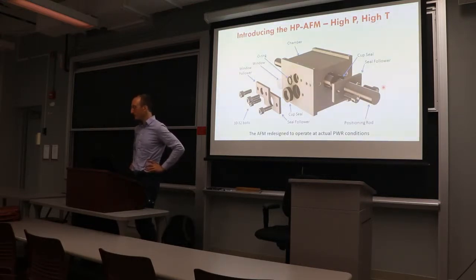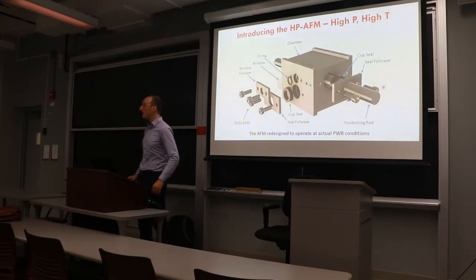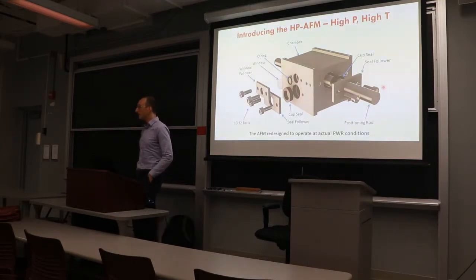What about thermal conductivity of these coatings? Doesn't matter. They're so thin. They're not as good as metals, right? These are ceramics. They're often not too good. But we only apply 1 to 200 nanometers. Like I mentioned before, the coating has to be thin, so you stay in that epitaxial limit, and we can't get these things to flake off. But if you grow them to be a micron or so, then 1, they become like a thermal barrier coating, and 2, they crack and flake off. So there's a sweet spot of a few hundred nanometers where it doesn't matter for neutronics, water chemistry, or adhesion.